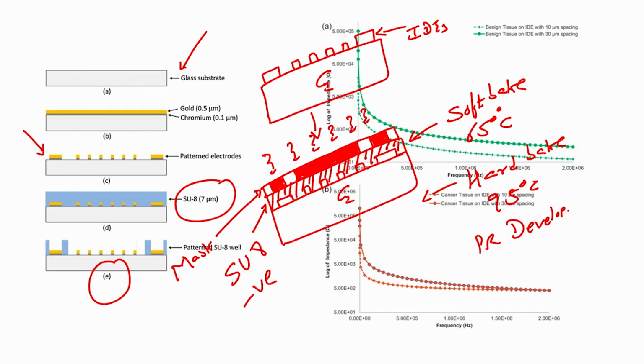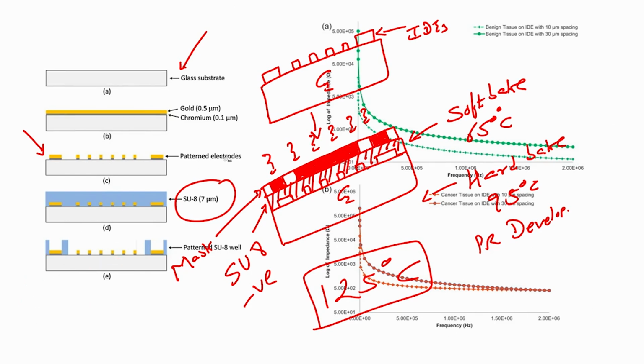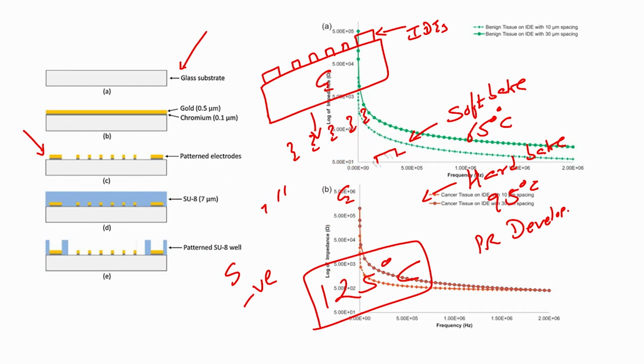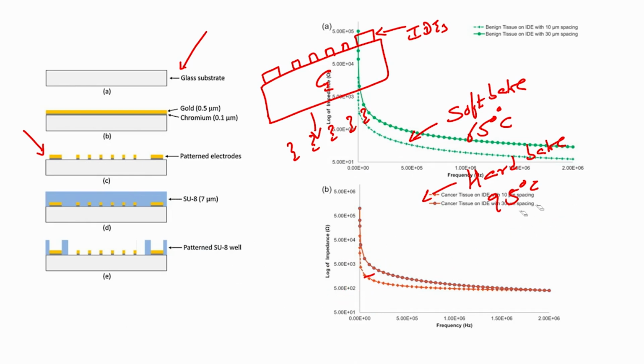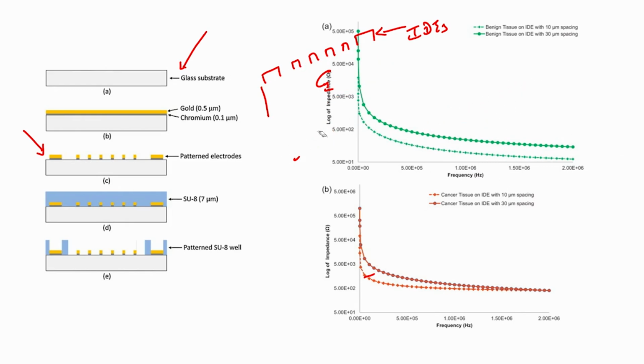number E, right. You can see here the area which was not exposed, the photoresist got developed, and then if you want to make the photoresist harder, you can further bake it at 125 degree centigrade for some time, right. Again depending on the thickness of the SU8 that you are using. Once you do that, you have your interdigitated electrodes inside the SU8 well, and now your chip is ready for testing the electrical properties of the cancerous and the normal tissues.